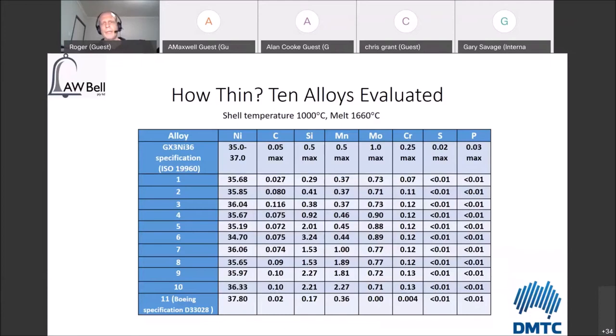One of the reasons why we went for the compositions that we did, we found that there was an ISO specification for an Invar type alloy called GX3 nickel 36, which is from the ISO specification 19960. Now the molybdenum in there has some very interesting effects to it. It doesn't have a very severe effect on some of the other characteristics of the material. So we basically just kept that at around the 0.7 to 0.9%, because moly does have some positive impacts on the outcomes that you achieve. So this was the starting 10 alloys.